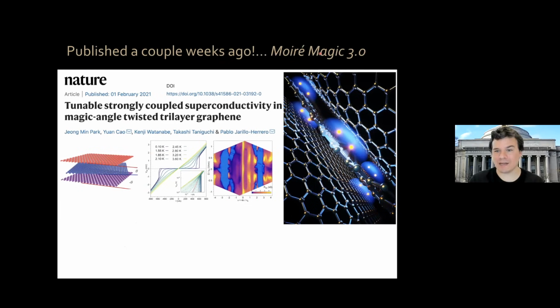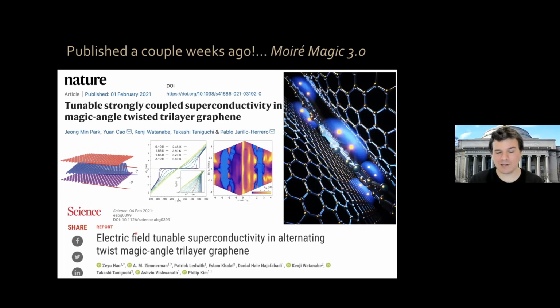I call this Moiré Magic 3.0. Okay, 3 layers. It turns out that when you put 3 layers arranged with special angles, also a magic angle, which is different from the previous magic angle, okay? The magic angle depends on the number of layers. You have an extremely strong superconductor, even stronger than the bilayer case, okay?